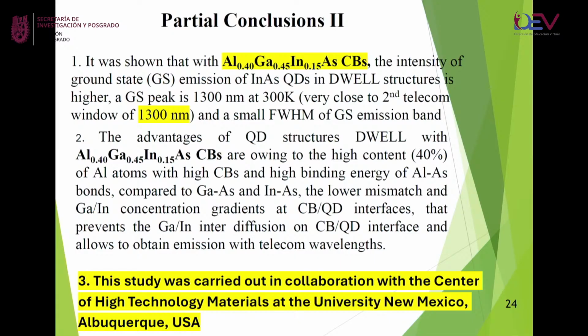This advantage for this material was received due to the higher binding energy of aluminium arsenide bonds, compared with gallium arsenide and indium arsenide bonds. And due to the smaller concentration gradient of indium and gallium, we include indium in the capping layer; we include additional indium in the capping layer. And due to this smaller gradient, it does not introduce a change in the composition of the quantum dots.